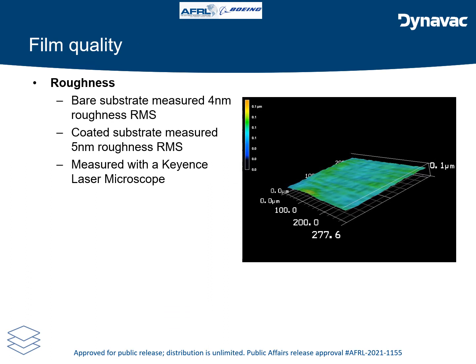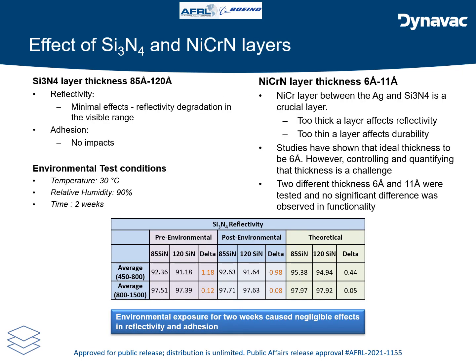Film quality. The roughness of the films was measured. Prior to putting in any protected silver coating, we measured the substrate roughness, and it was about 4 nanometers. Post-coating, we also measured the roughness, and it was about 5 nanometers. So this tells us that the coating does not increase the roughness drastically, which benefits in obtaining better optical properties.